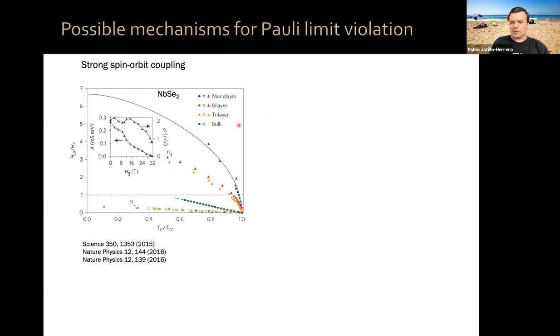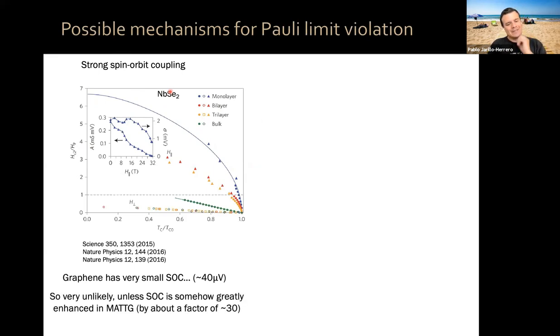So these transition metal dichalcogenides violate the Pauli limits, but these systems are well known to have very strong spin orbit coupling. There's this Ising superconductivity in these systems. However, graphene has a very small spin orbit coupling, of the order of 40 microvolts. So it's very unlikely, unless for some reason, and we haven't found any theories that were able to tell us a good reason for this, but unless spin orbit coupling is enhanced by almost two orders of magnitude in magic angle twisted trilayer graphene, it would be very unusual that spin orbit coupling would be responsible for the observation of our data.